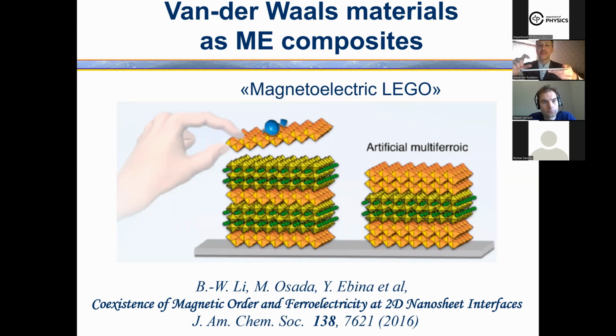So in this case, you form a special structure with nanopillars of, for example, ferroelectric phase and a magnetic matrix. And when you apply an electric field, nanopillars can be stretched like strings. It's much easier due to the reduced clamping to the substrate. It's much easier then to deform. So in this case, the magnetoelectric effect can be enhanced in the composite.